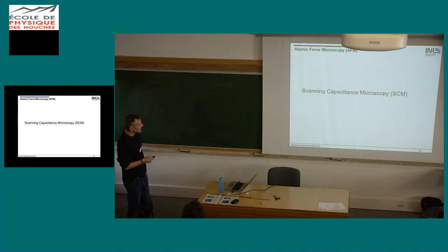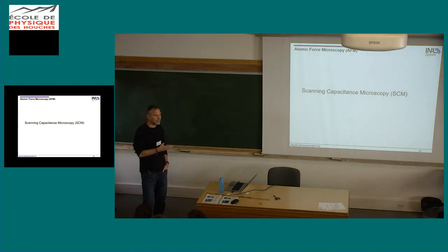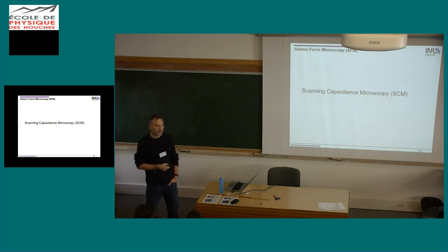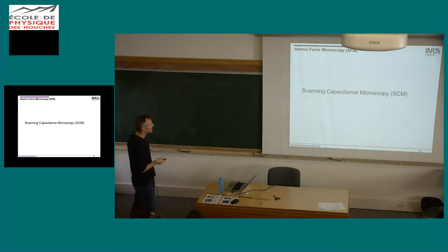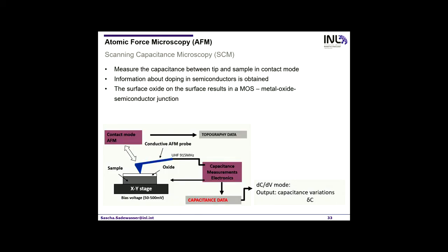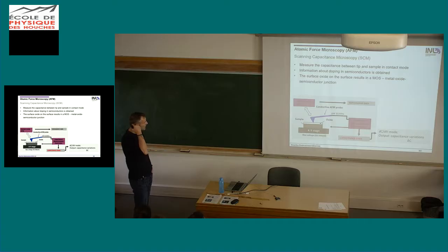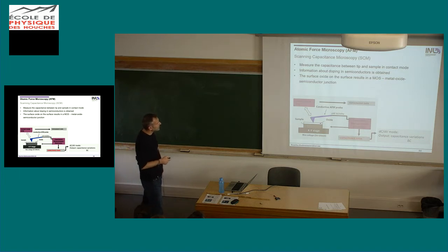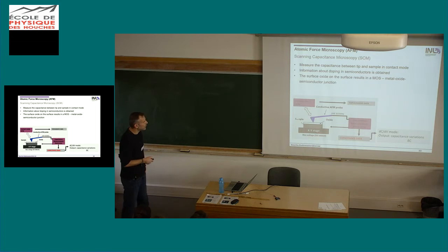So I start with scanning capacitance microscopy. Obviously, we always look at semiconductors. Capacitance, we heard already yesterday in the tutorial. We could actually make capacitance voltage profiles. We were not taught how to do this, but it was there. So capacitance is a quite important property in semiconductors, or a useful measurement. Here you want to measure the capacitance between tip and sample, and for this you go into a contact mode. And this provides information about the doping in semiconductors.